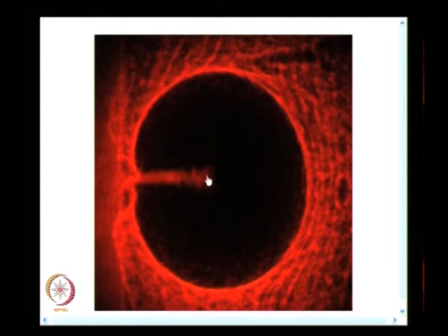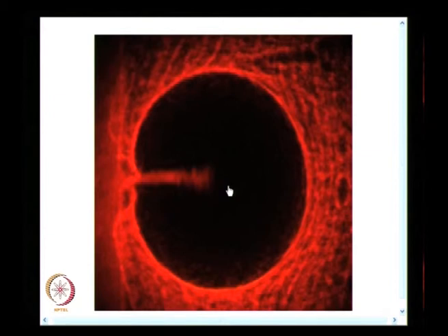So, you send a beam of light, you get a shadow, you do not get light passing through, and that is mainly because the specimen behaves in a fashion where you have a thickness change. Whatever light rays impinge on it, it diverges, it behaves like a divergent lens, and you do not have light here, and that becomes a shadow, and that is what you see on the screen.